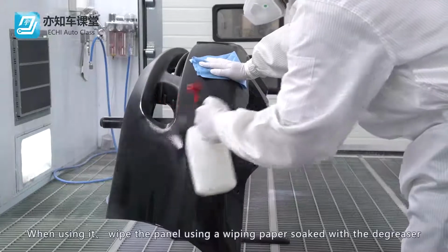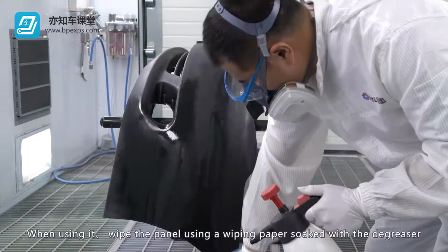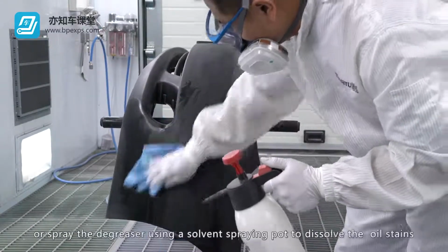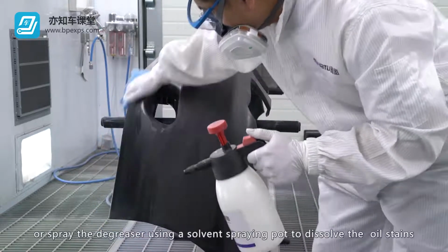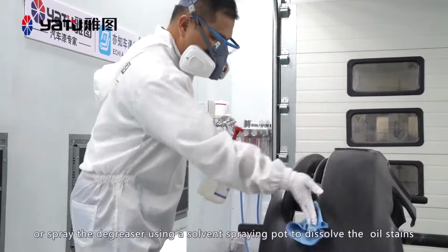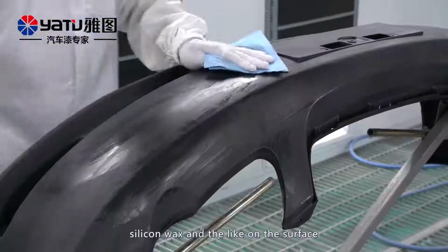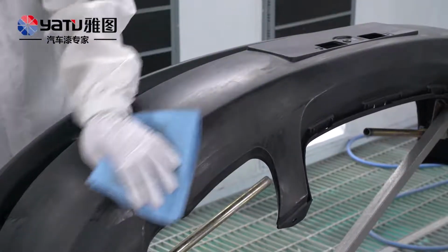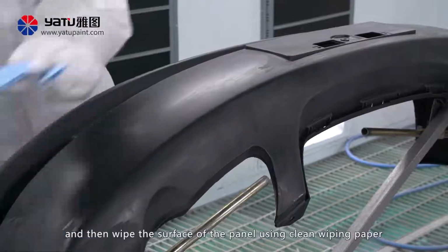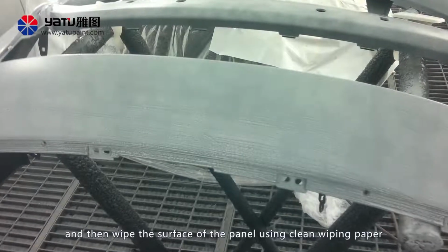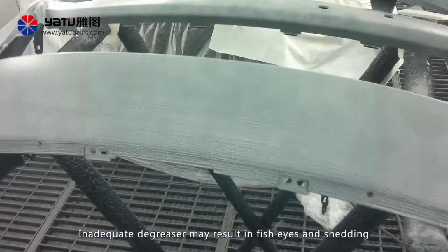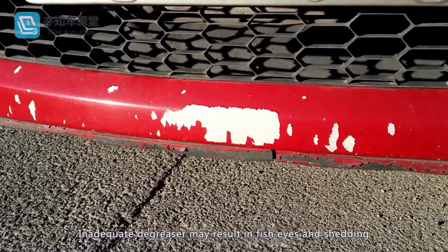When using it, wipe the panel using a wiping paper soaked with the degreaser, or spray the degreaser using a solvent spraying pot to dissolve the oil stains, silicone wax, and the like on the surface, and then wipe the surface of the panel using clean wiping paper. Inadequate degreaser may result in fish eyes and shedding.